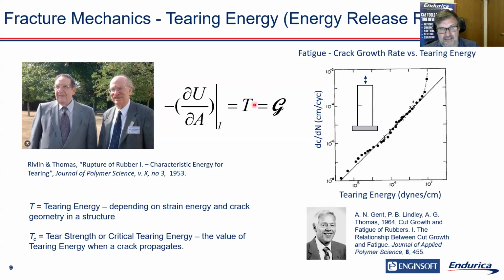We also see that this tearing energy or energy release rate characterizes well the crack growth rate, the amount of crack growth with respect to cycles for a fatigue loading situation where we have cyclic loading, where the maximum tearing energy is going to be well below T sub C, but due to the number of cycles, you're going to get some crack growth. We'll see a lot more on this curve later on, but this is crack growth rate versus energy release rate, typically plotted on a log-log plot. They used funny units that we don't use anymore back in 1964.